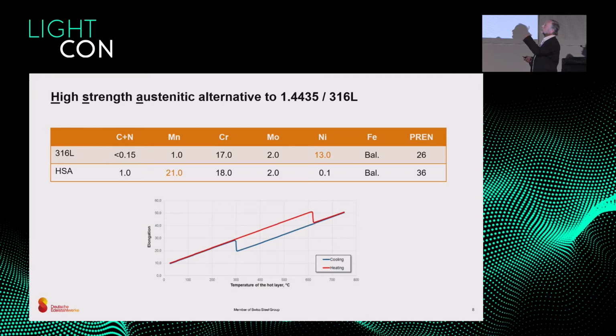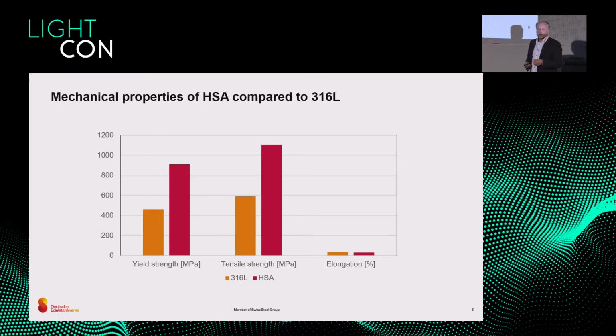With this alloying with carbon and nitrogen, we avoid the formation of the martensite. We have stabilized the austenite. So in this model, we stick on the blue line for the complete building of the component. Here are the mechanical properties. The red line is the new grade HSA.